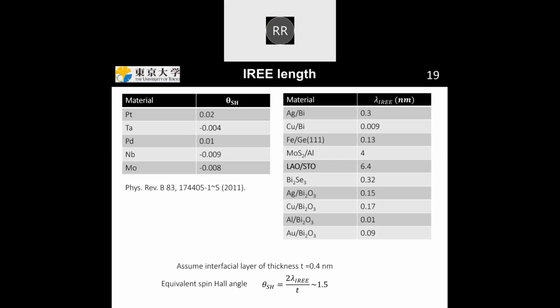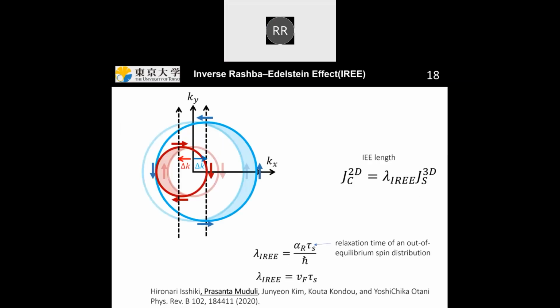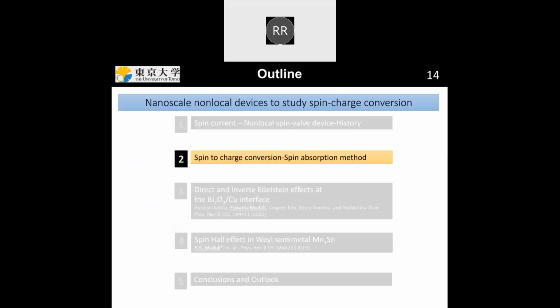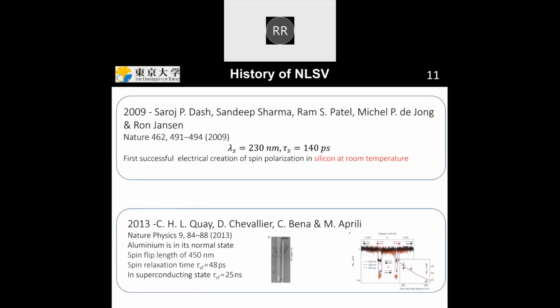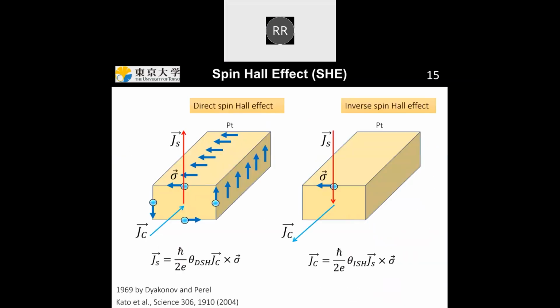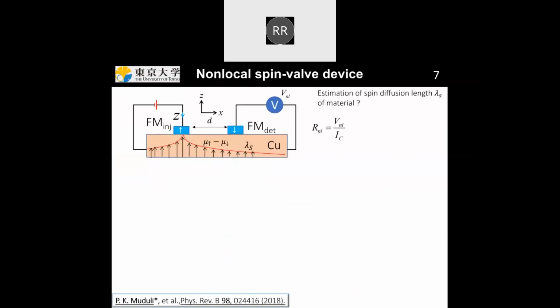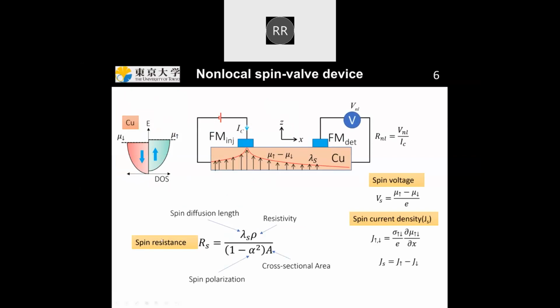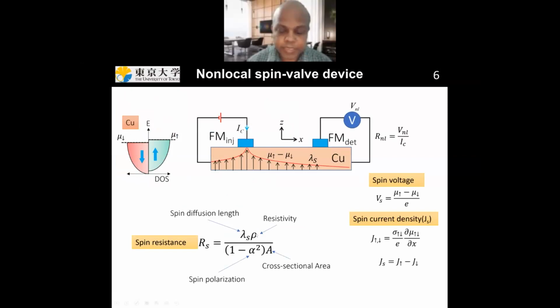Hello. Yes, sir. So I want to know, sir, about spin resistivity and spin mobility. On which parameters will this spin resistivity and spin mobility depend? Okay, let me go to the next slide. Yeah. So here, the spin resistance is defined like this one here, which depends on the spin diffusion length, the resistivity of the material and the spin polarization of the material. And suppose you have a nanowire, it depends on the cross-section area of your nanowire.